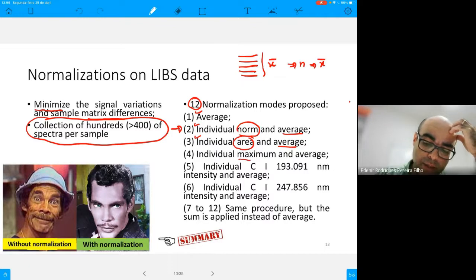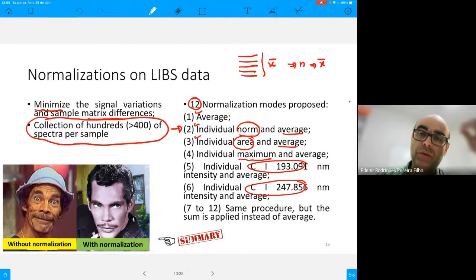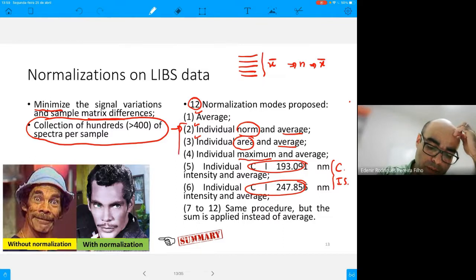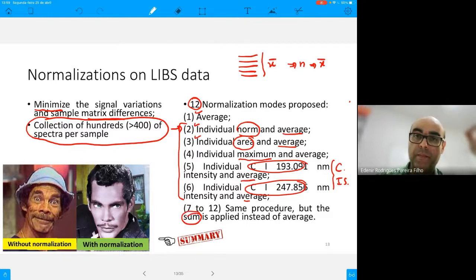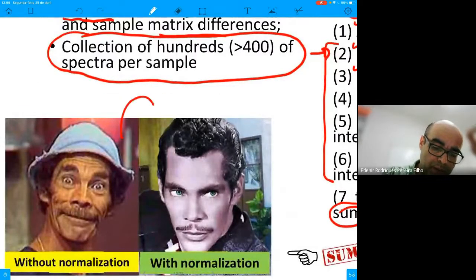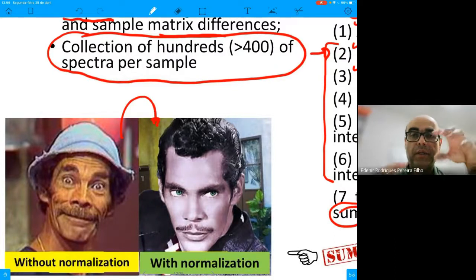We can normalize by the maximum, by the line 193 or line 247. You can use the carbon line here as an internal standard. And we can perform these normalizations here using the average or using the sum. Okay, the main goal is to, I like this joke here, is to transform the data, reducing the variation among samples with the same characteristics.